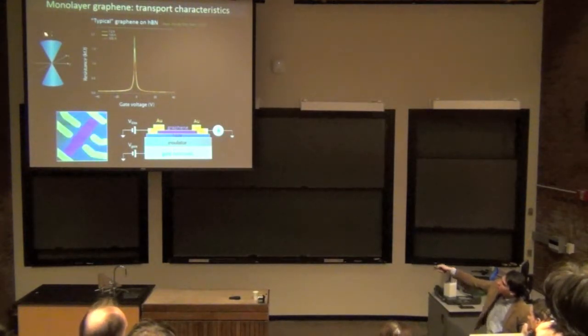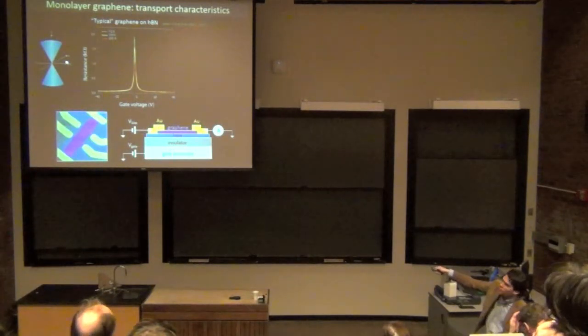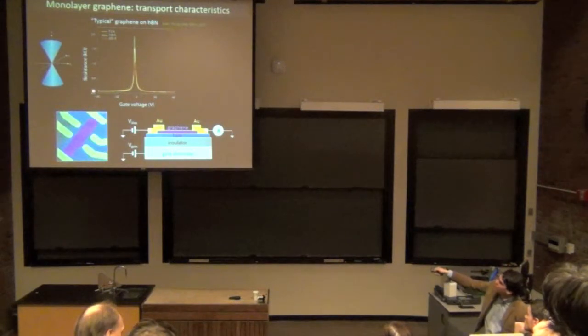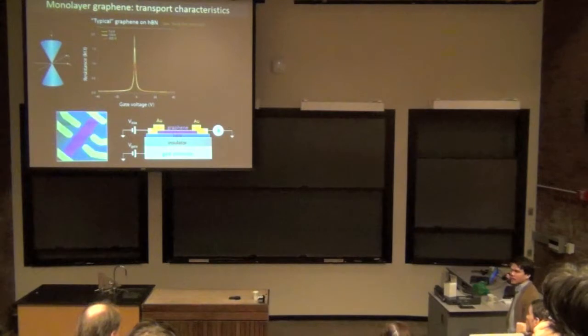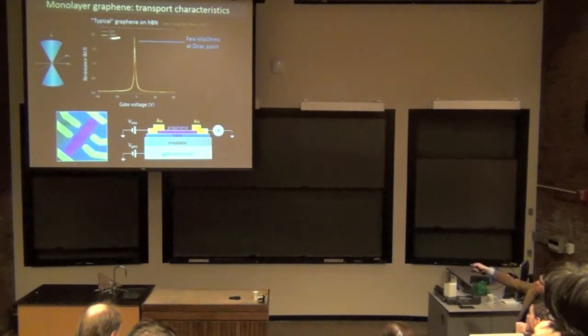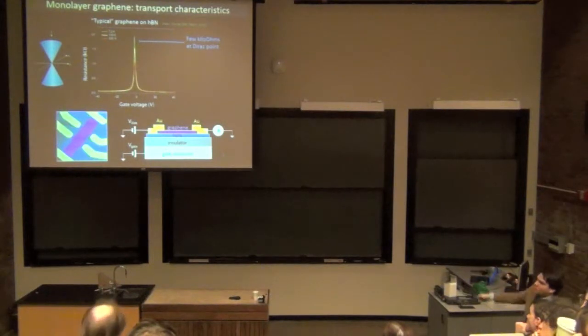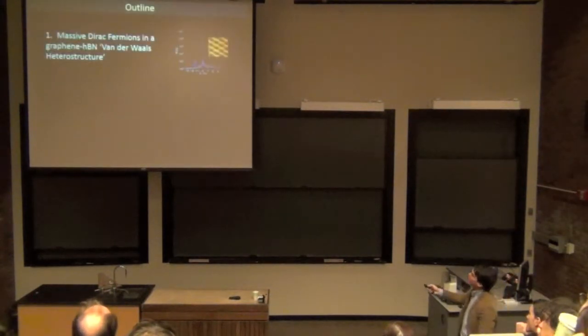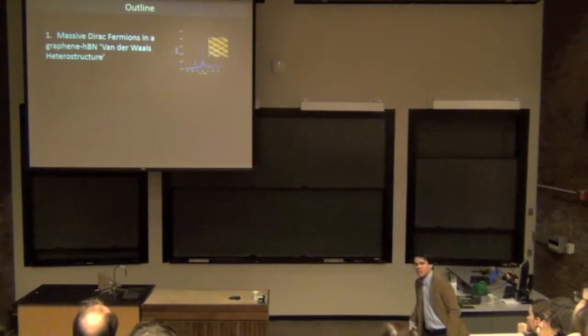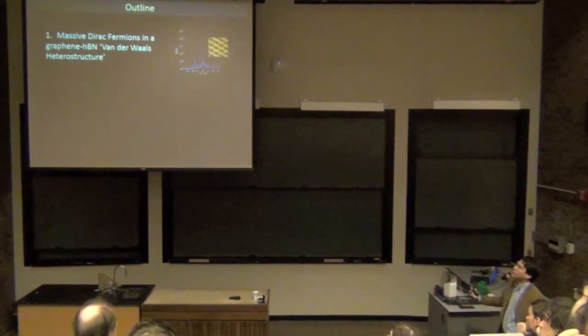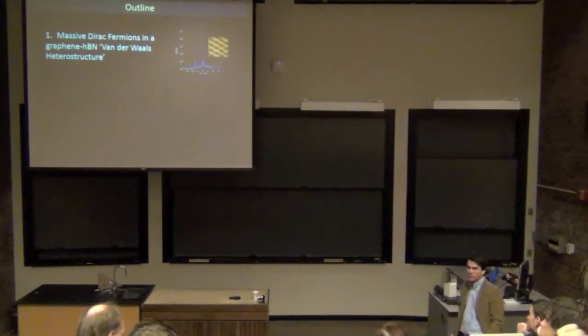And when we tune the gate, or when we tune the conduction from holes to electrons, we pass through this Dirac point, this so-called charge neutrality point. And what you see, the transport signature of that is a peak in the resistance as a function of the gate voltage. So just remember that this is what normal graphene looks like, and that the resistance of this device is a few kiloohms when the Fermi level is sitting at the Dirac point. Okay, so that's basically where we were, where the field was when I started working on this about 2 years ago.